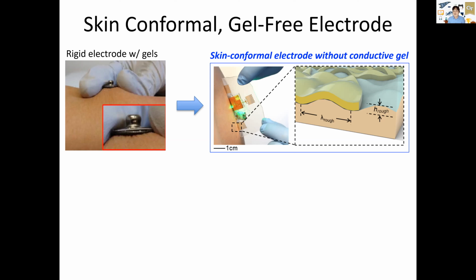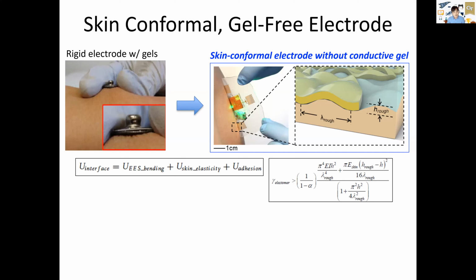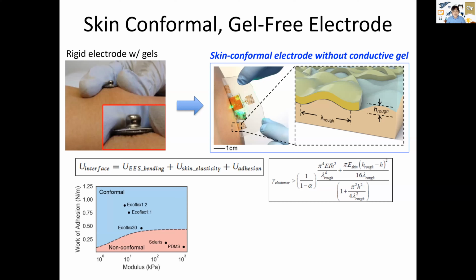So on the right-hand side, once our sensor is ultra thin, then now it can follow the morphology of the skin, okay? So we don't need to use any conductive gel to cover the gap between sensor and the skin. To understand better the interface between sensor and the skin, we developed this analytical equation that includes the sensor's bending energy, skin's elastic energy, and adhesion. Based on this study, we got this graph that captures the relationship between the work of adhesion of the substrate embedding a sensor and the modulus.